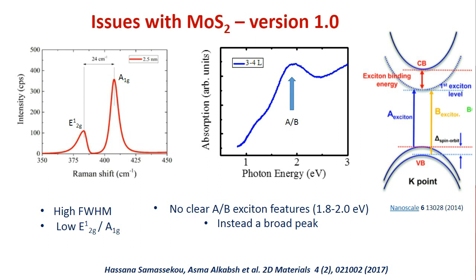So coming back to the issues with MoS2, as I was saying, the Raman modes were particularly broad, and also when we put this sample through our Shimadzu spectrometer, we were expecting that around 2 eV, which is slightly above the band gap, a doublet feature, and these are called excitonic features. So we were expecting that around 2 eV there would be 2 sharp peaks. Instead, we found 1 broad peak.